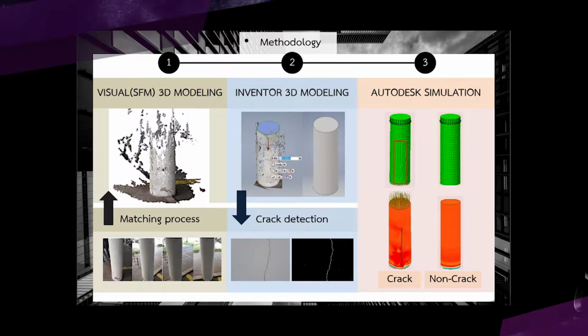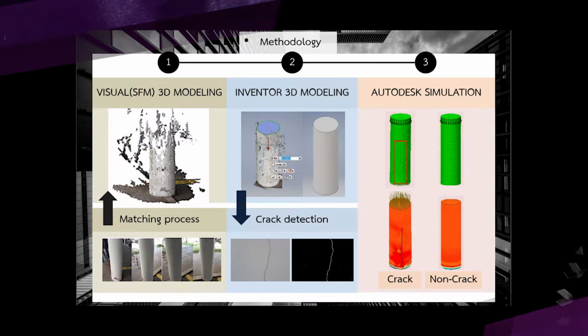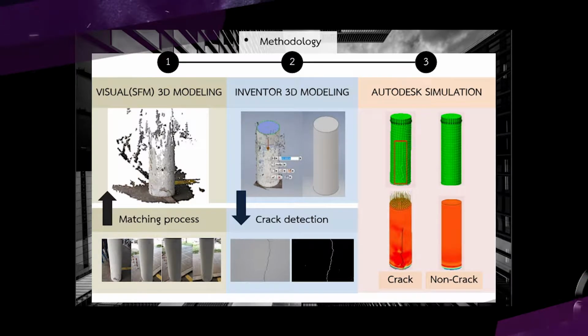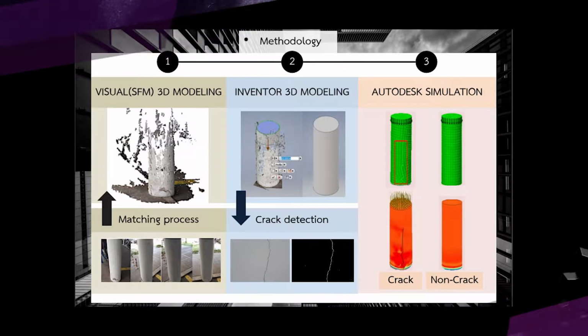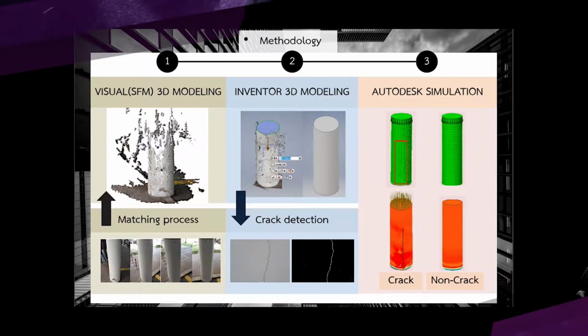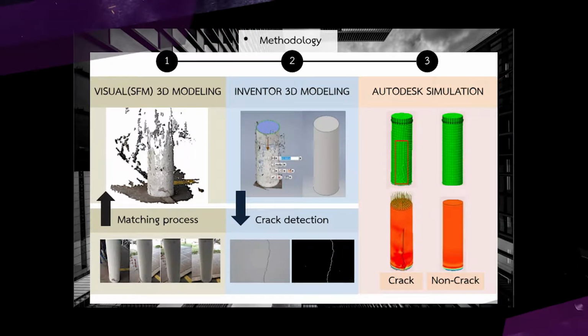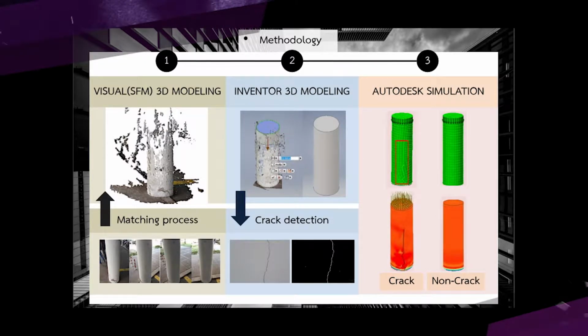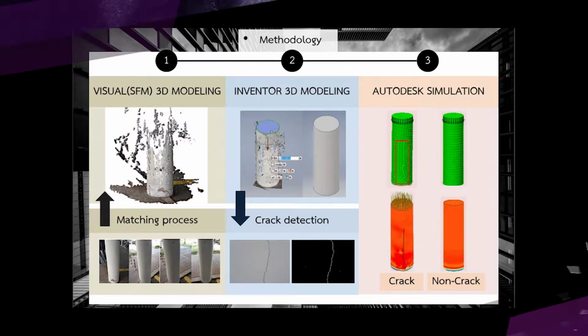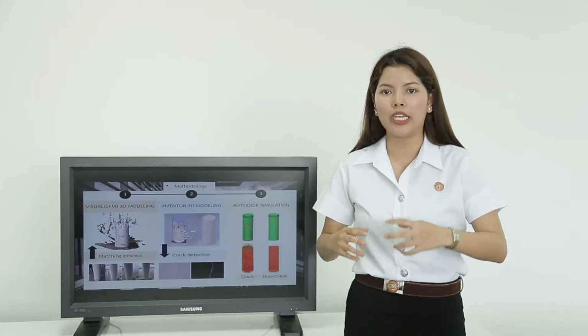The final step is 3D finite element modeling with cracked and non-cracked structures using the Autodesk simulation application. This simulation application will analyze the displacement, stress, and strain of the cracked and non-cracked structures. After we analyze the stress values, we compare the cracked and non-cracked structures to prove that the cracked structure model has a weaker and lower strength capacity than the non-cracked structure. That means the cracked structure has a higher risk of collapse in the future.